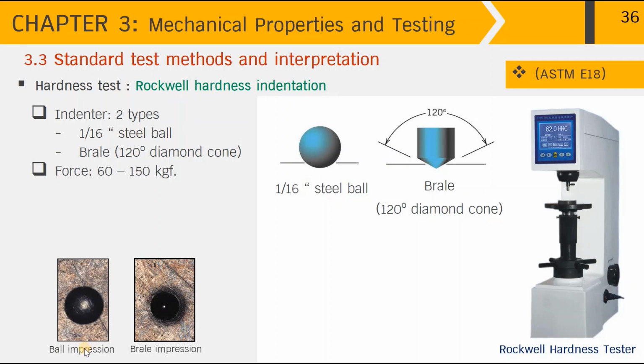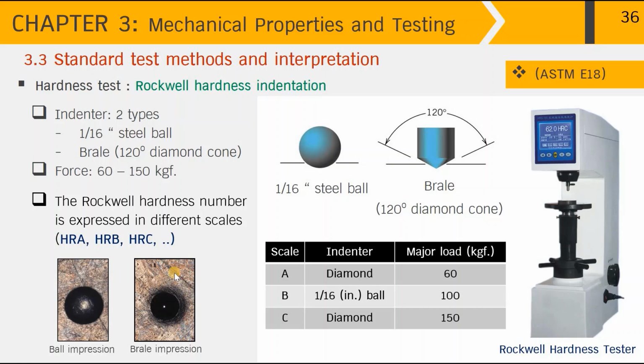The first one on your left-hand side is the indentation obtained from a ball-type indenter, and the one on your right-hand side is the Brale impression. For Rockwell hardness test, there are a range of scales, but for now, I will introduce you to just 3 scales: HRA, HRB, and HRC. For each scale, we have to select the proper indenter and the major load so that we can get the standard test result.